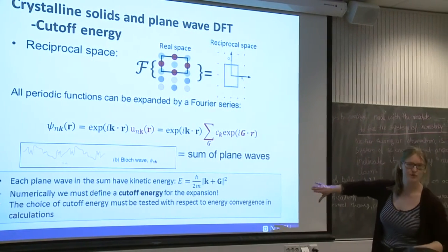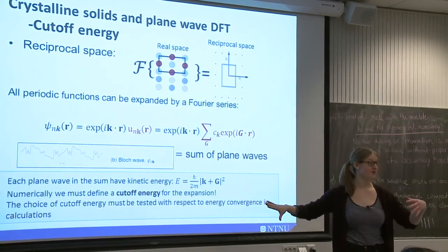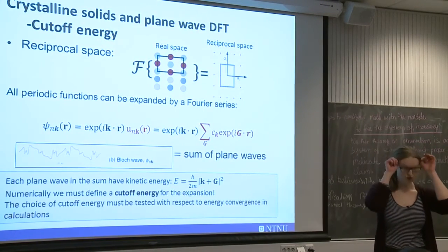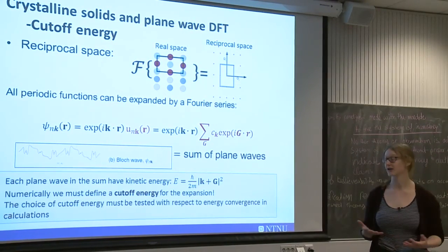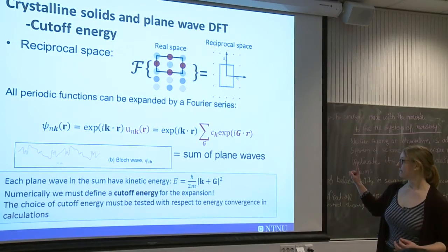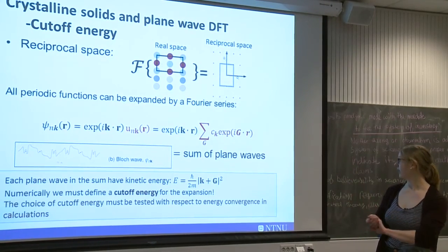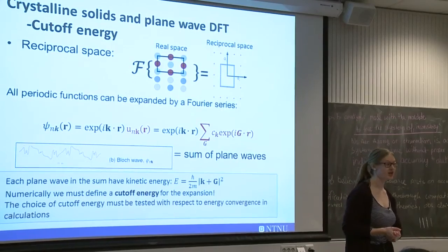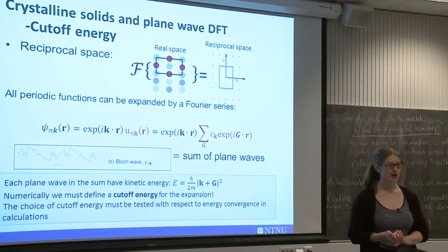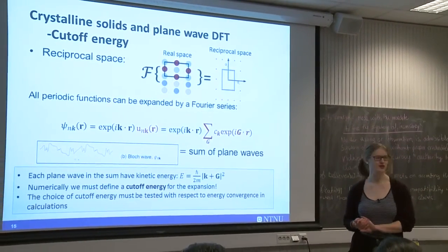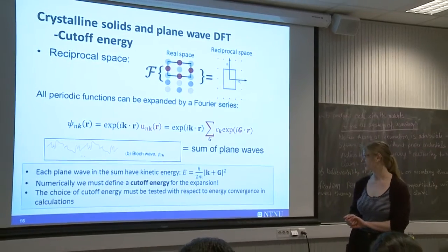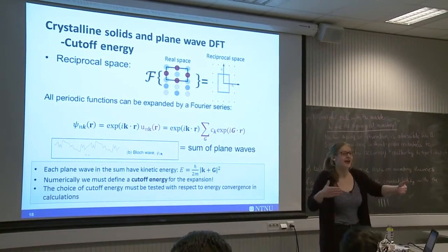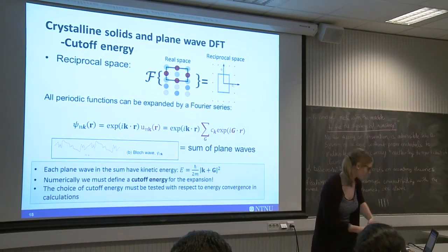So this is a really important input parameter for you when you do these calculations yourself. And I'll come back to how you actually choose this cutoff energy, because you have to do convergence testing in terms of your total energy to choose a high enough cutoff energy.